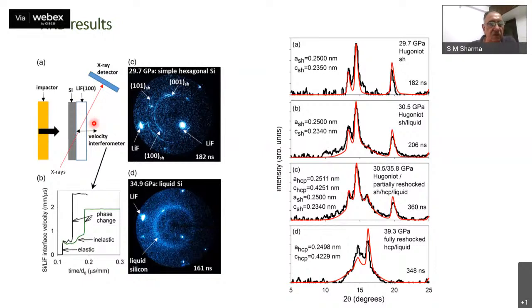Recall that sometime back we talked about the interaction of shock waves with various interfaces. This has a lower impedance than this. As the shock travels into this, it bounces back but reflects another shock into this. So if the initial longitudinal stress was, let us say, some value, after reflection it will be more. This we call reshock. For example, if we shock this initially to 30.5 GPa, then after reshock from lithium fluoride, the silicon was taken to 35.8 GPa.